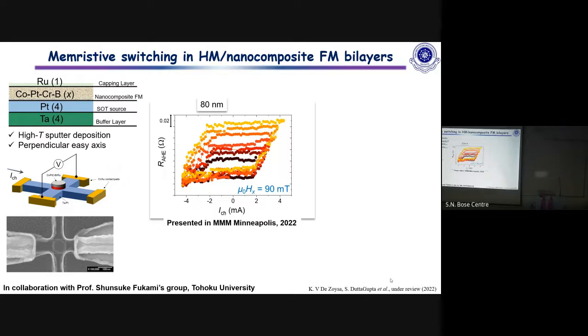But you don't have any antiferromagnetic part. Sorry? Don't have any antiferromagnetic part. No, this is a ferromagnet. You don't have any bias. Yeah, actually, we tried with that. The problem is that, at this point of time, we are not able to get perpendicular anisotropy with the antiferromagnet below. For some reason, if we put platinum manganese, this material just falls in the plane or shows a lot of problems. Some more work needs to be done in this department.